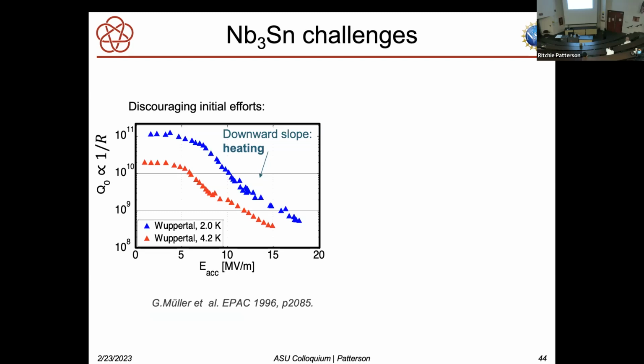So people have been trying this for a while. Back in the mid-90s, here's the accelerating gradient and the quality factor. And it looks really great when the accelerating gradient is low. But when people tried to push the accelerating gradient, the quality factor dropped, the resistance was going way up. Nobody understood. It looked horrible.